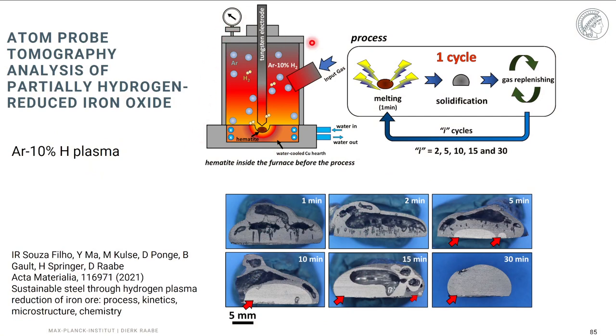Here you see these gigantic graphite electrodes that typically are used for melting down the scrap. But here we have built a little reactor where we do a very similar experiment. We flood the reactor chamber with argon and add about 10% of hydrogen gas. And then we ignite the plasma in the material, and we do it always for durations of 1 minute. Then we stop the processes, take the specimens out and test them regarding the iron content that was formed, put them back into the oven, flood the oven chamber with the same gas mixture and ignite the plasma again. And by that we could show that after already 15 minutes and definitely after 20 to 30 minutes, you have under these conditions produced pure iron directly from the ore.